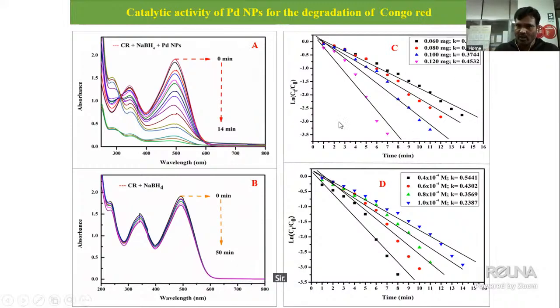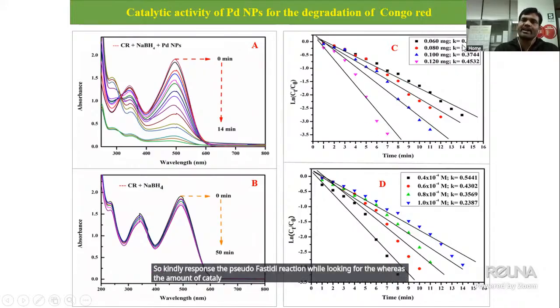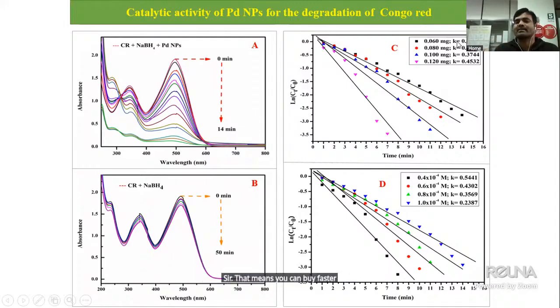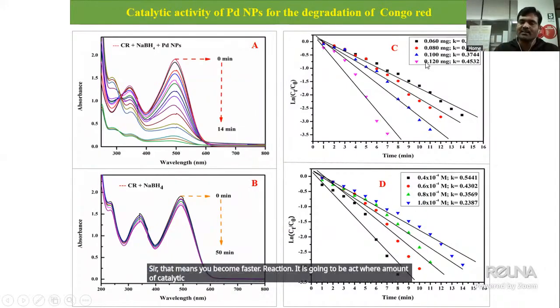Further, we identify the kinetic plot, which follows a pseudo first order reaction. As the amount of catalyst increases, the rate constant increased. That means a faster reaction occurs. As the amount of catalyst increases, there is more surface activity and a greater number of active sites. Then ultimately the dye molecule degradation is faster.